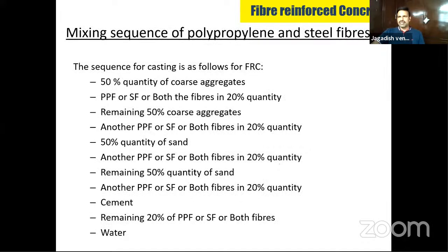This is very, very important. Many times people will miss this: the mixing sequence. When you are making fiber reinforced concrete, you have to be very careful and alert. Listen, many don't follow it. They dump everything, cement, coarse aggregate, fine aggregate, fibers, including water, in one shot and then mix it. But in the case of fiber reinforced concrete, this is very important.